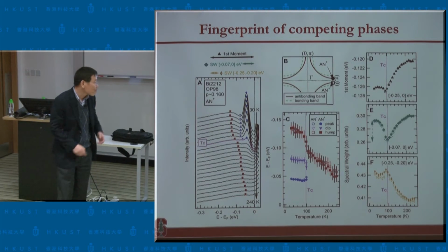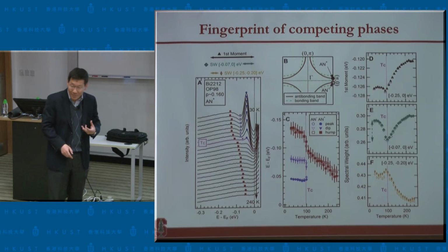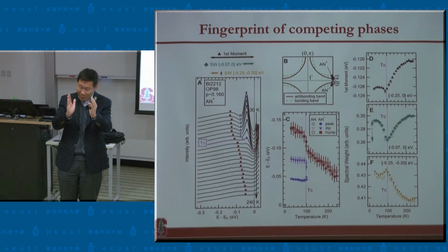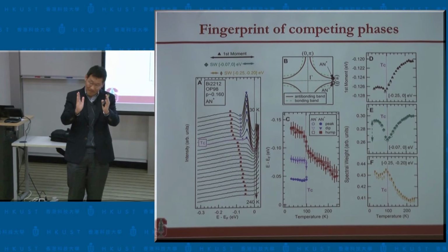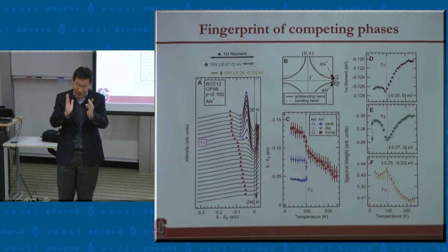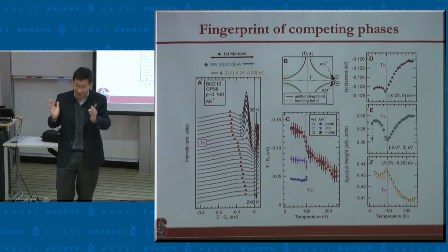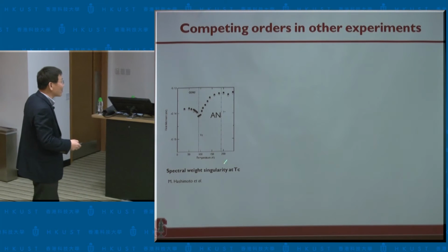The fact that this goes in the opposite direction is a direct indication that the superconductivity destabilizes the pseudogap state. Let's say I have a pseudogap that has opened up an energy gap. Now, if I open up another gap, traditionally you think about two gaps adding up in quadrature, so you'd get an even bigger gap. No, this data suggests that the superconducting state actually competes. That means you basically restore the spectral weight that was taken away by the pseudogap.